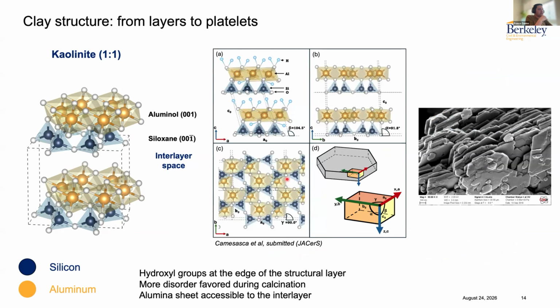Now, it's important as well to realize that these materials have a layer structure at the lattice level, but they also have a habit of precipitating layer crystals. And in order to distinguish these two, we are going to call layers the lattice units, and we are going to call platelets what we see, for example, in an SEM. And of course, the unit cells are oriented within these platelets, but they are not the same thing. One platelet thickness may have hundreds of stacks of these unit cells all pointing within the same direction. In general, we have the z-axis pointing towards the short axis of the platelet.